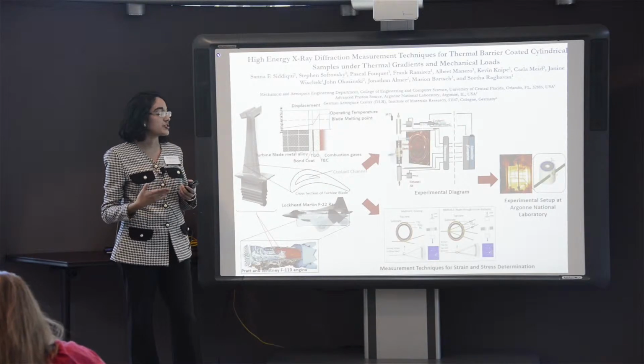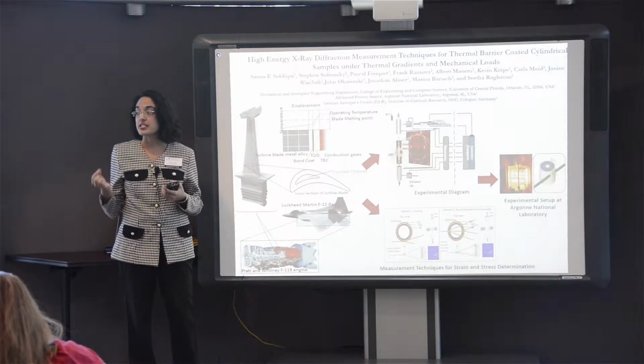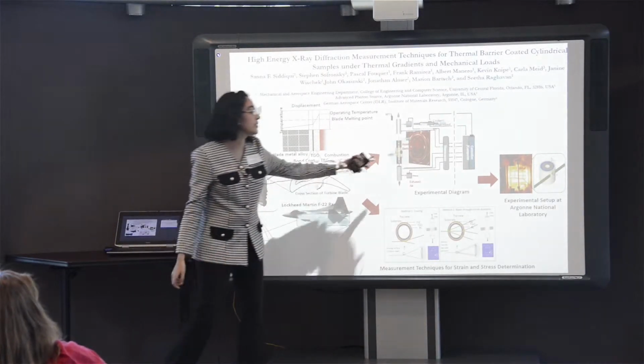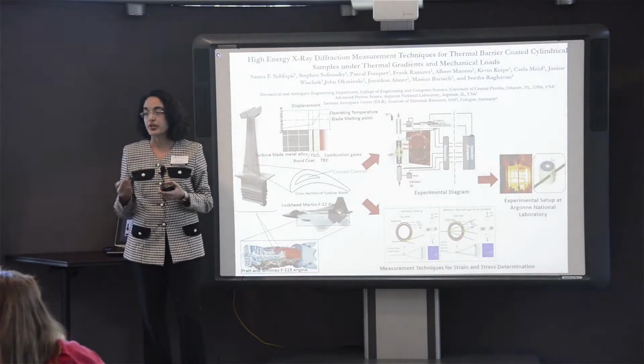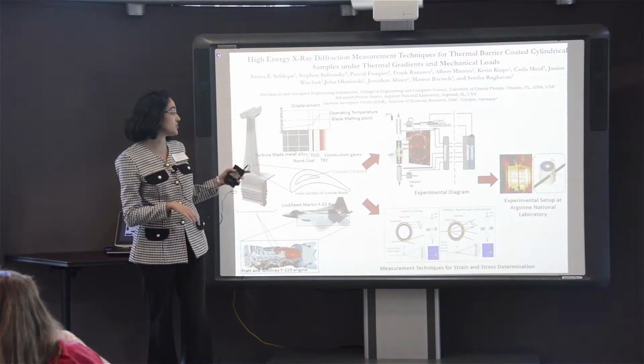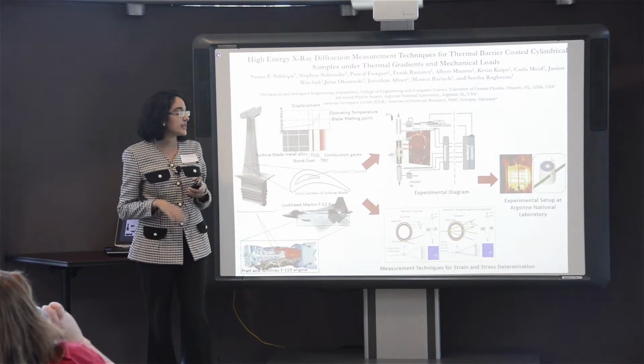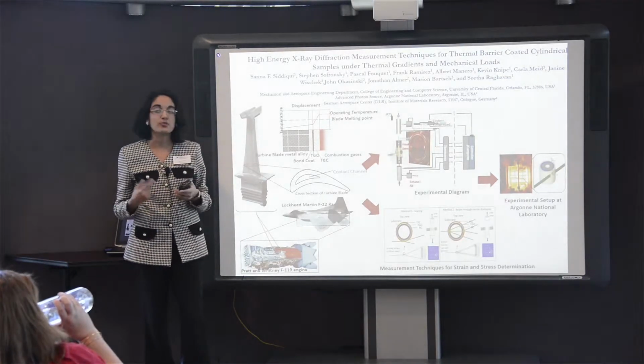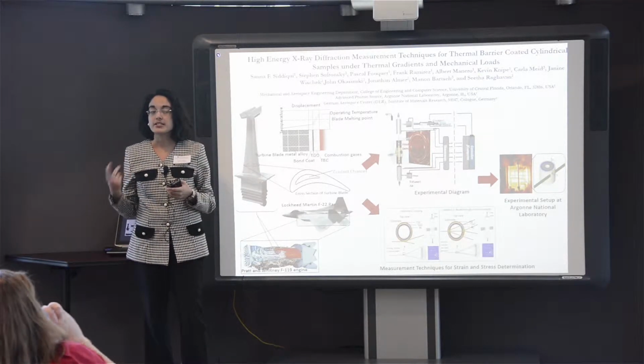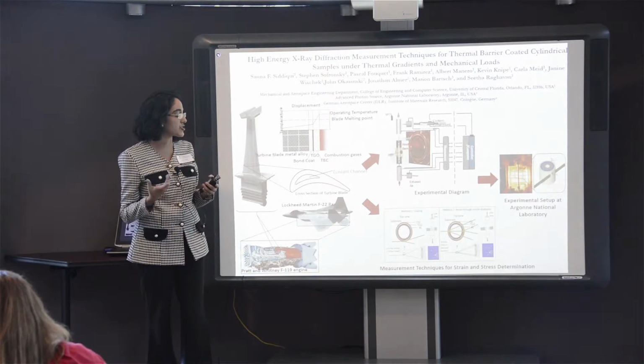So what we've been able to do is first create a cylindrical sample geometry, which is shown over here, which is coated with the thermal barrier coating, and this is representative of the turbine blade. And basically, we have developed 2 measurement techniques through synchrotron or high energy X-ray diffraction methods.